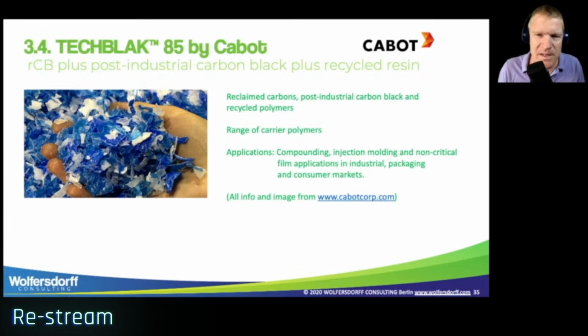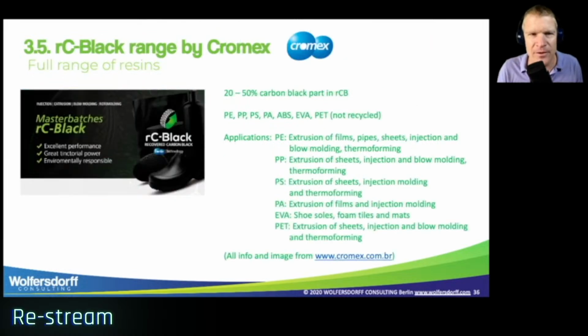So this is out of specification carbon black, which cannot be sold, and which normally is being blended into normal carbon black at a very low rate of 1%. But if this can be used for a plastic master batch, that's also a good application. And it contains recycled polymers. Cabot make no statement of whether it's post-consumer or post-industrial. And there's a range of carrier polymers. Applications are quoted as compounding, injection molding, and non-critical film applications in industrial packaging and consumer markets. Again, all info and the image is from Cabot.